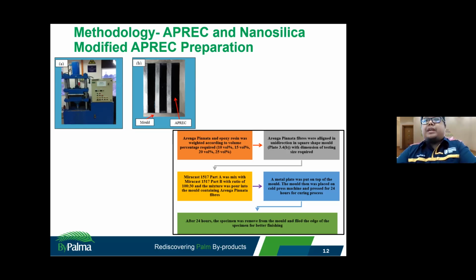Okay, we use this mold size because we want to avoid the push from the unidirectional Arenga Pinnata. We want to get only a single angle from the arrangement. Okay, after that the Miracast epoxy was poured in the mold containing Arenga Pinnata fiber, and then we put a metal plate on it and put it in a cold press machine and pressed for around 24 hours for the curing process.